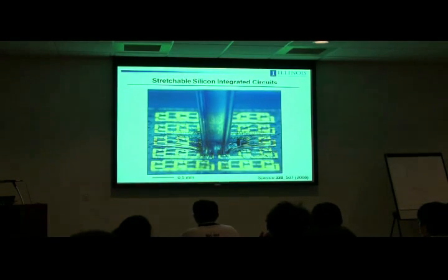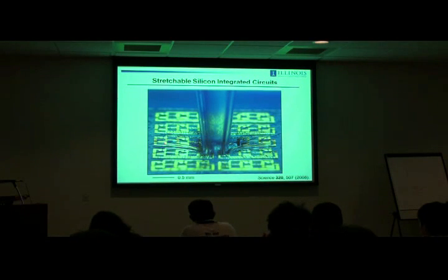One is range of stretchability. The other thing is that because this circuit is all interconnected together by that underlying sheet of polyimide, when this thing is pressed down, the silicon transistors see a bit of strain also. And the strain couples to mobility. So depending on how you're stretching or twisting or torquing this thing, the current outputs in individual devices could fluctuate up and down by maybe 20%, just due to that strain-induced change in the electronic properties. And depending on the circuit design, that may or may not be a problem.